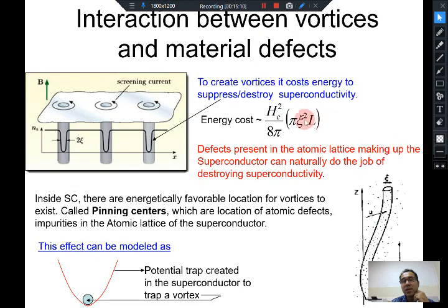So these different techniques give you interesting ways to measure the different properties of the superconductor. If you measure the amount of flux in the vortex core, you know what is the charge state of the Cooper pairs. Is it 2e or e? You actually know that. Okay, and that's how it was proved that there are Cooper pairs. If you measure the size of this core, you can get an estimate of your coherence length. If you measure the distance over which the magnetic field is distributed, for example in the scanning Hall technique as it was done, you can measure the penetration depth of the superconductor. So the vortex core actually gives you a handle on many aspects of the superconductor.